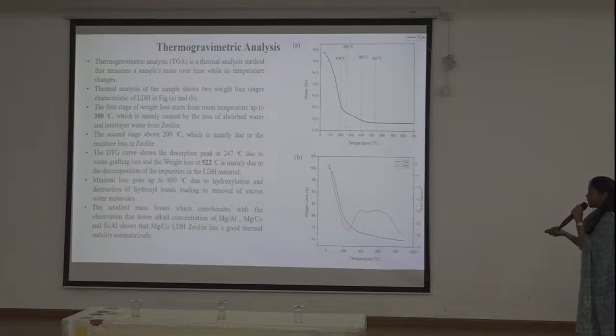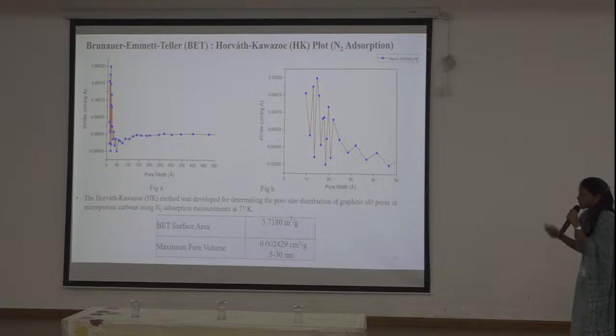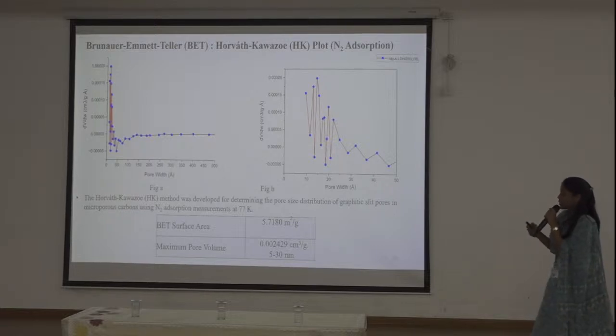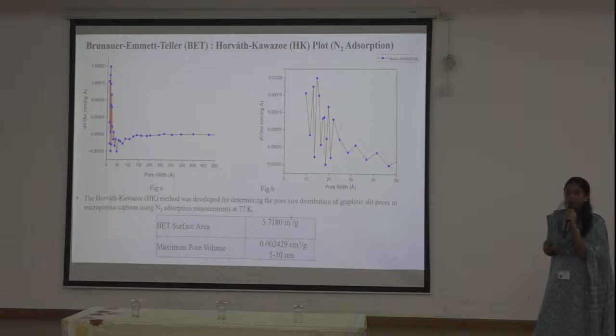We confirmed that magnesium cobalt LDH has good thermal stability compared to magnesium aluminum LDH. BET analysis was taken for the material, since pore size is very important for zeolites to trap CO2 molecules on its surface.